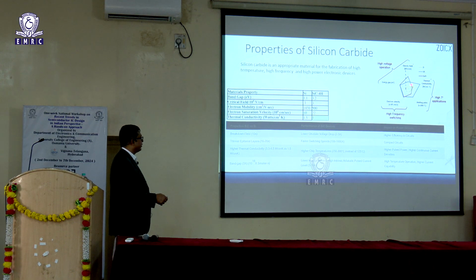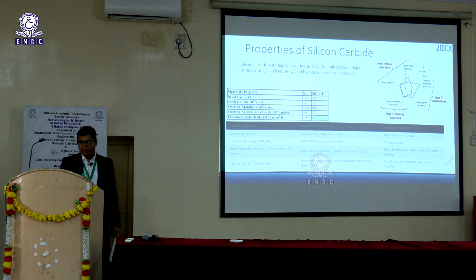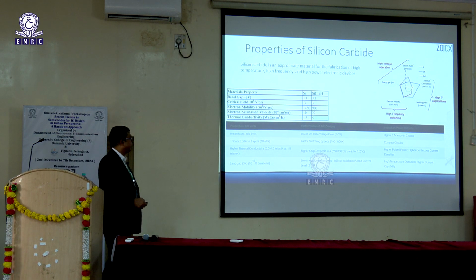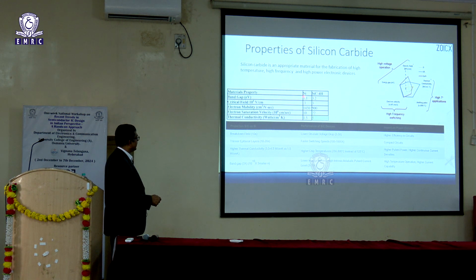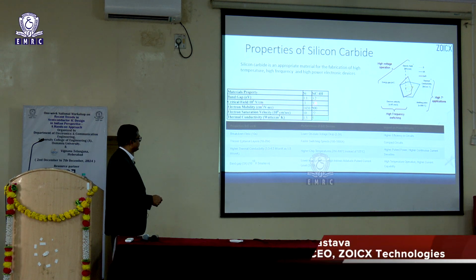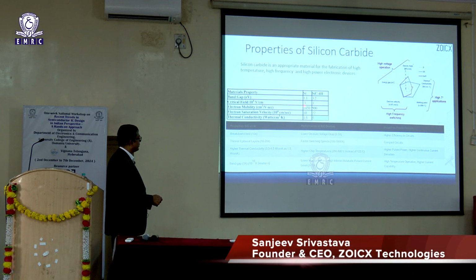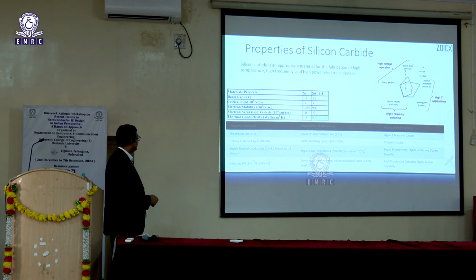And you see the silicon is the inside circle, which means for these particular properties, both silicon carbide and gallium nitride function better than regular silicon. And if you see here the material properties, a comparison between silicon and silicon carbide, band gap is 3 times. The critical field that it can withstand is also 10x. This is 0.3 and this is 3.